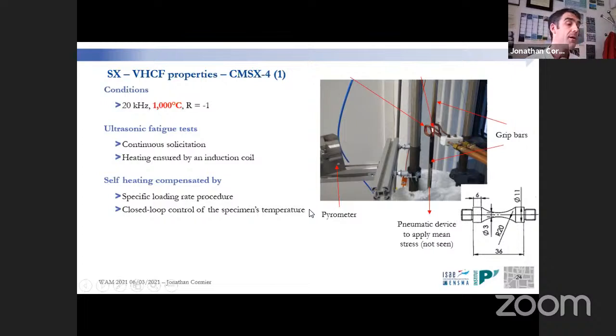Those conditions are really important from a certification point of view, because airworthiness authorities impose criteria with respect to high cycle fatigue, very high cycle fatigue failure at such frequencies, because a blade can vibrate in bending mode during service, and we need to take into consideration possible failure due to this. So the machine we have, and we have a second machine under development here, typically uses induction heating, temperature measurement with a pyrometer, and we are coping with possible self-heating during the test.